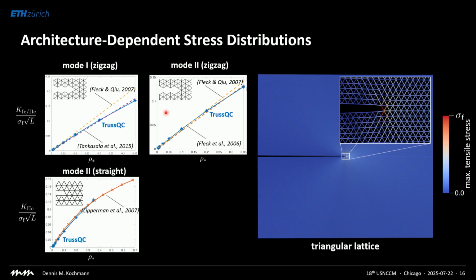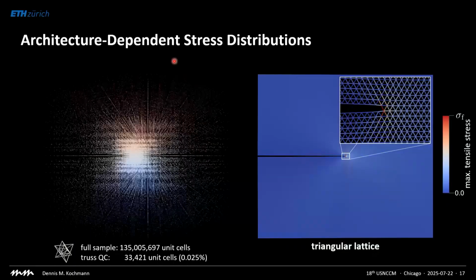If you take the triangular lattice over here, a triangle is elastically isotropic. If you homogenize it, you get exactly the same modulus in every direction. But once you introduce a crack, that's not true anymore. All of a sudden, it matters. What matters is what exactly is the orientation of your crack relative to the orientation of the triangles. All of these things we can easily figure out with computational tools.